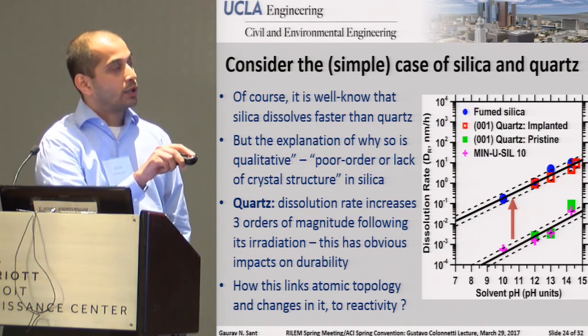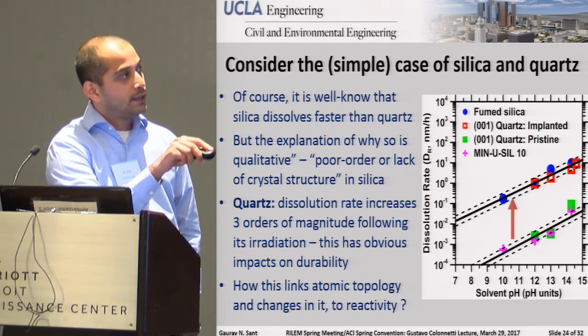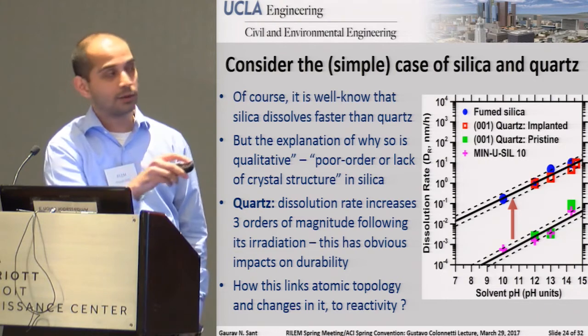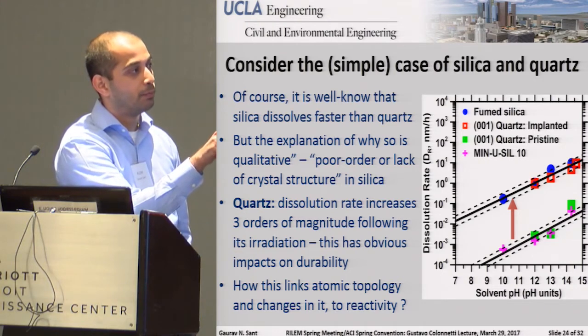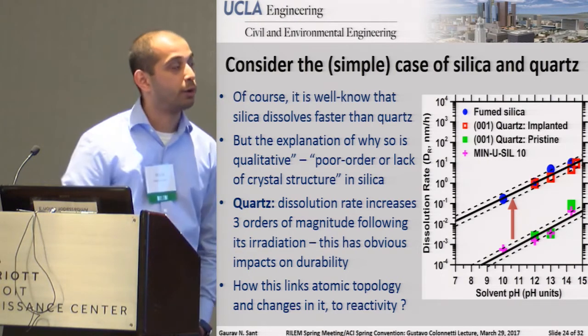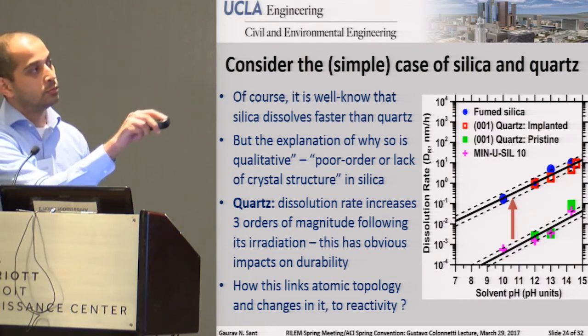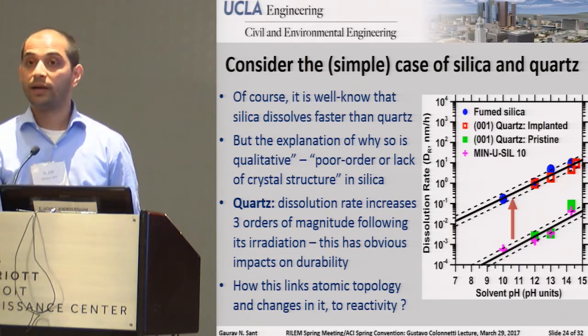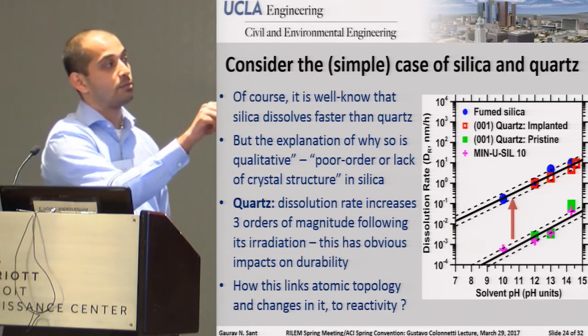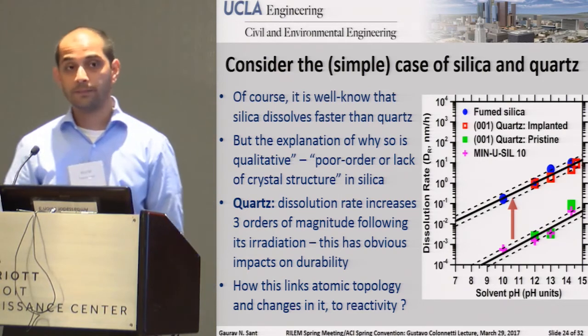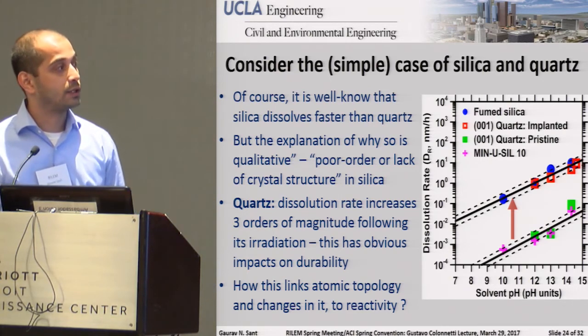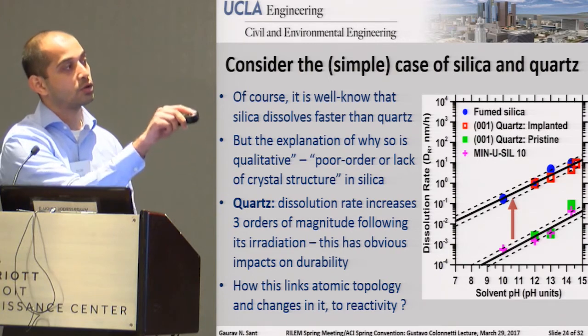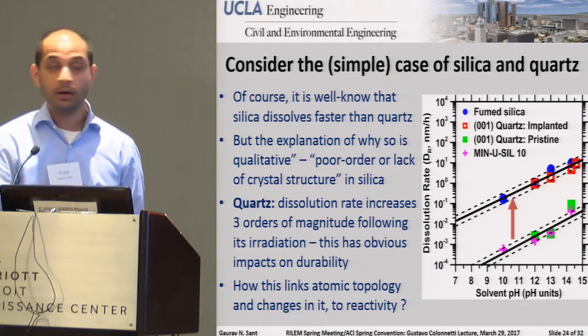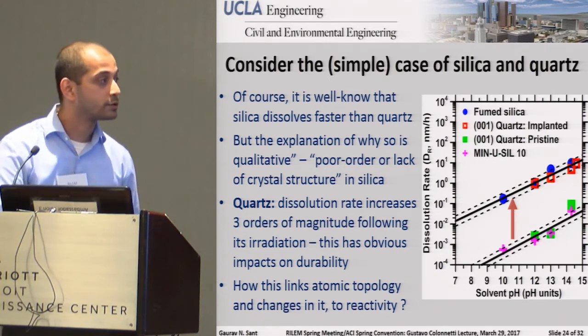One thing I want you to note is that you go from quartz, which is pristine, doesn't matter whether it's a single crystal or polycrystalline, the pink crosses show you polycrystalline quartz, to quartz following irradiation, it actually perfectly starts to match the dissolution rate of amorphous silica. So the reason that this is important, the first thing to point out, is you're getting about a 3 orders of magnitude increase in dissolution rates by simply amorphizing quartz.